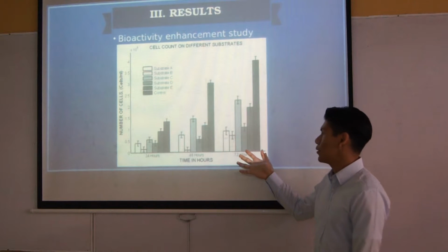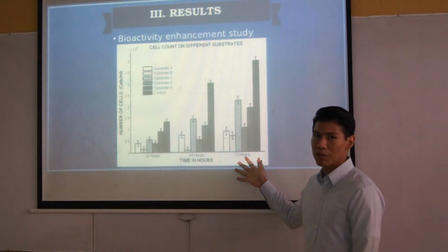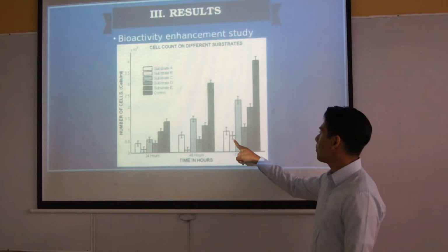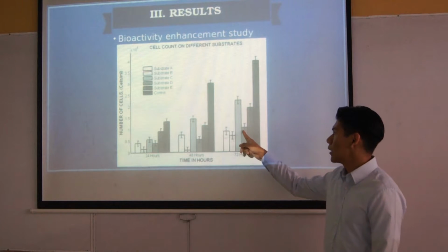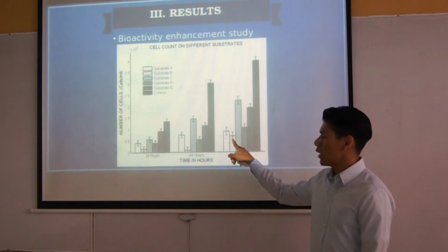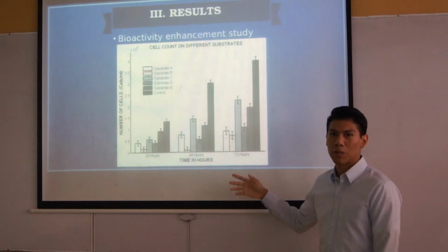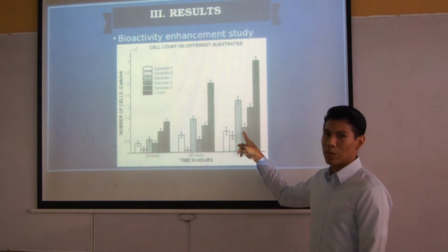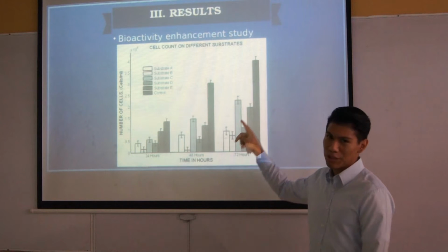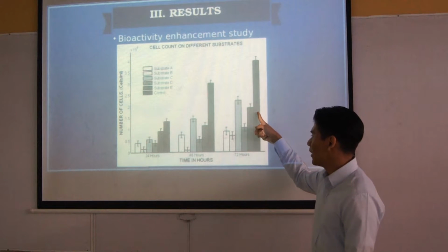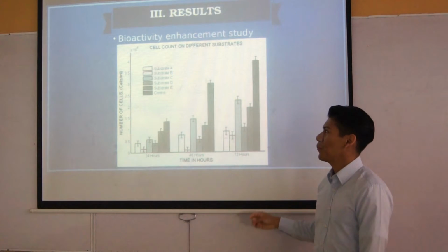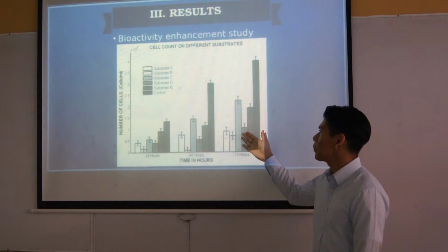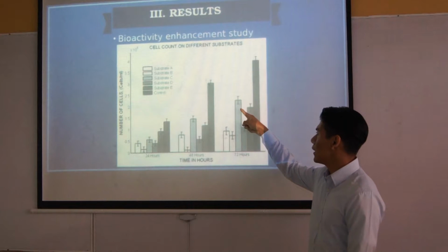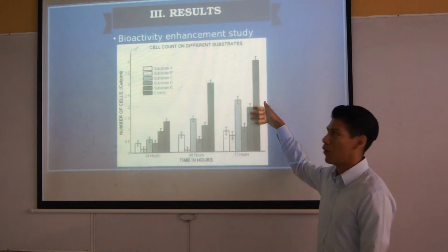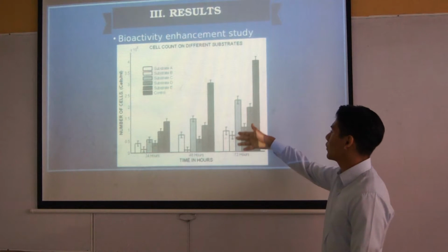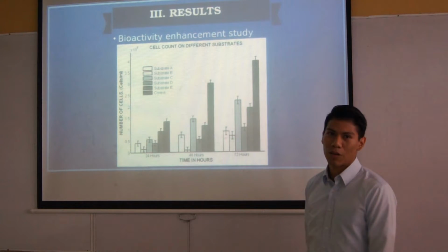In the final day, 72 hours after the cultivation of cells, we observe that probes A and B are not significantly different from probe D. And these probes A and B, as we recall, are the substrates altered with porosity, and probe D is 100% polymethylmethacrylate. The only differences are probes C and E, which exhibit a high bioactive behavior when compared to probe D. What we note here is that probes C and E are not significantly different from each other. And of course, they are always constrained by the upper limit, which is the control substrate.